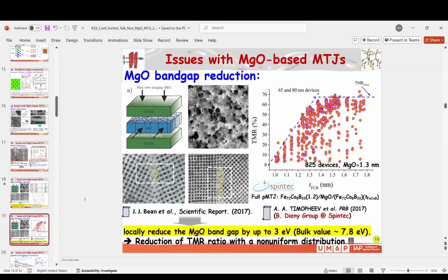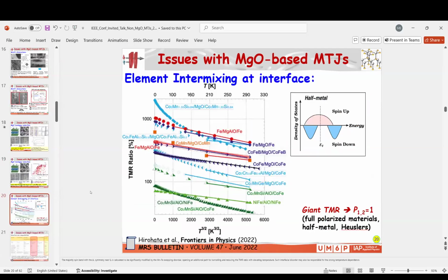In my understanding, this can be overcome by using alternative barriers. Here I'm presenting the performance, and I refer to this brilliant report by Professor Hirohata from Tohoku University. He gathered all the data from MgO-based MTJs and their performance from high temperature to low temperature, 330 K to low temperature, and you can see the increase of the TMR at low temperature, of course.